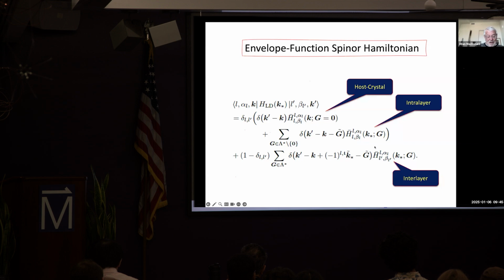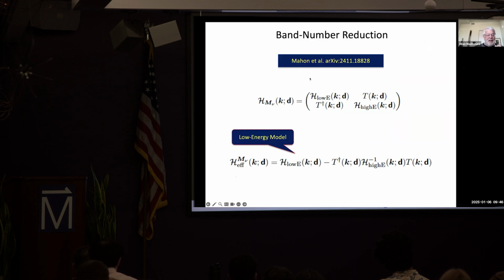And these position dependent terms can be just evaluated at the center, so K star here, at the center of the momentum range of interest. So you end up with an effective Hamiltonian, that's the host Hamiltonian, plus a bunch of momentum transfer scattering terms that capture the Moiré physics and produce momentum shifts, and they're all evaluated at the central momentum, both intralayer and interlayer terms. And so here's the thing I was stumbling over before. There was an equation on the previous slide that should have been deleted. Here it's expanded.